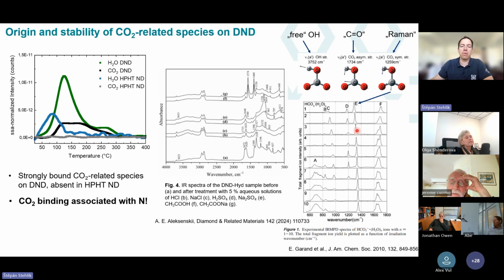And when we found this paper, we suddenly got explanation for all these strange additional peaks we saw in the IR spectra of DNDs. So, for example, this little sharp peak here, which we also ascribed wrongly to some free OH on some hydrophobic interface, it's quite probably actually the OH vibration in the bicarbonate molecule. Then the always present residual carbonyl is also from the sorbed bicarbonate, and the Raman 1332 or similar frequency is also quite probably the stretching CO vibration,